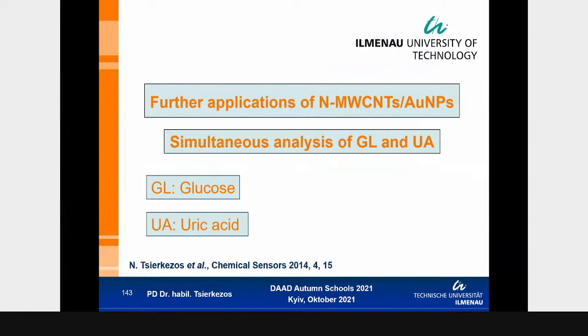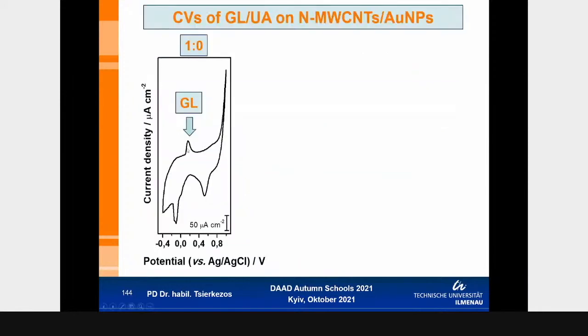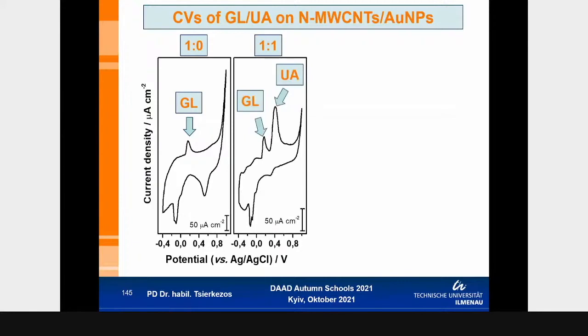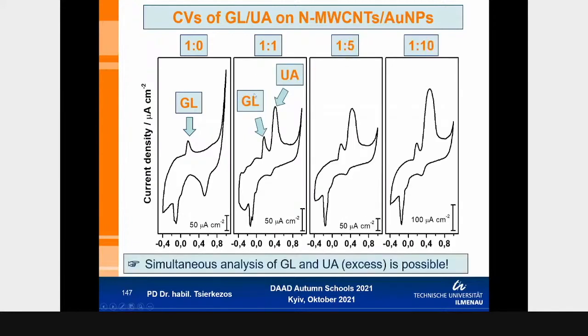I have tried, for example, to oxidize glucose on the nitrogen carbon nanotubes modified with gold nanoparticles without the enzyme which is required for the oxidation of glucose, and I have observed a peak at about 0.2 against silver chloride for the oxidation of glucose. And I added as well uric acid in the solution, and I tried to detect uric acid in the presence of glucose, and I have observed a second peak, which means that uric acid can be measured in the presence of glucose, and glucose can be measured in the presence of uric acid. But as I tell you, it's important that glucose can be oxidized in the absence of the enzyme, which is required for oxidation.